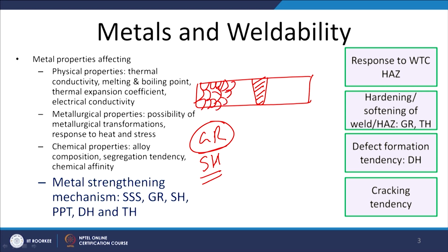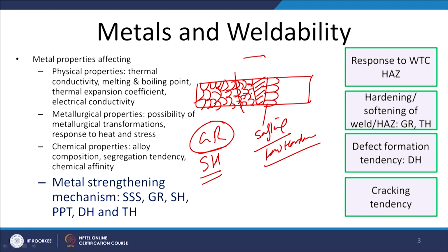like this. But when the weld thermal cycle is applied, due to the excessive rise in temperature in the zone next to the fusion boundary, all these fine grains get coarsened like this. So, coarsening of the grains next to the fusion boundary zone leads to softening and low hardness zone formation. So, here what we may have is, like the weld is harder, but the HAZ is weaker, then the base metal is stronger.